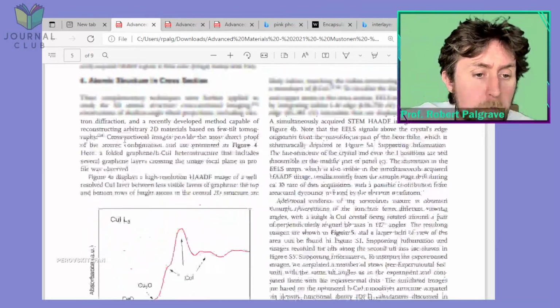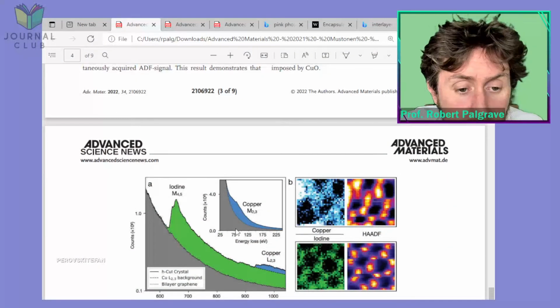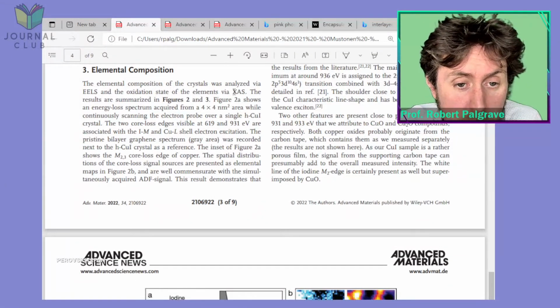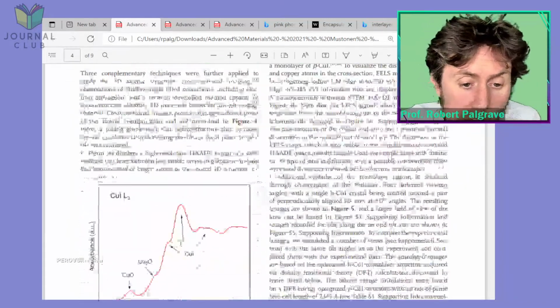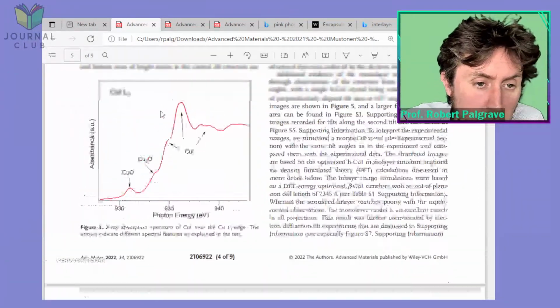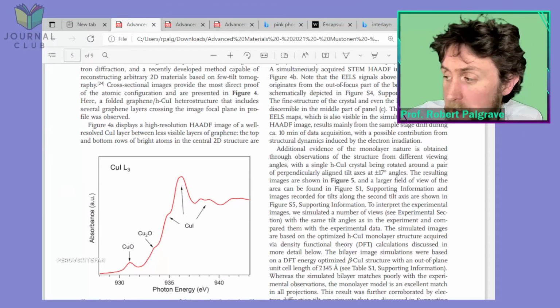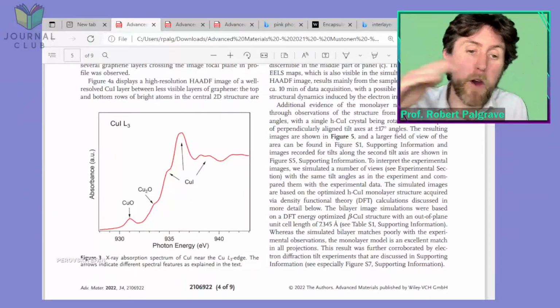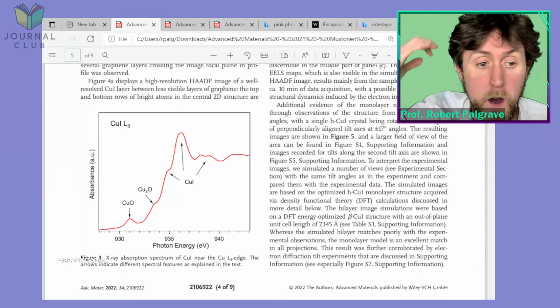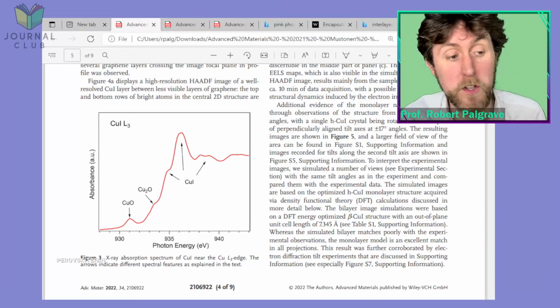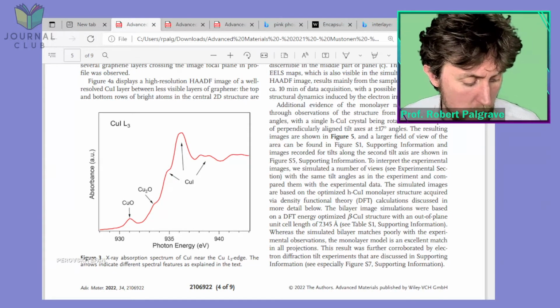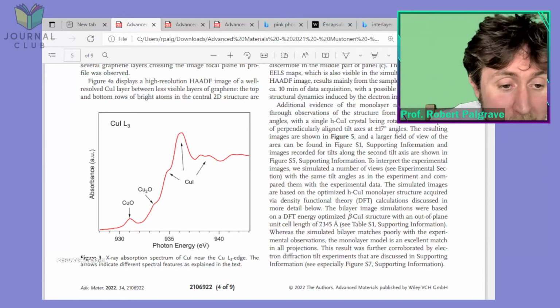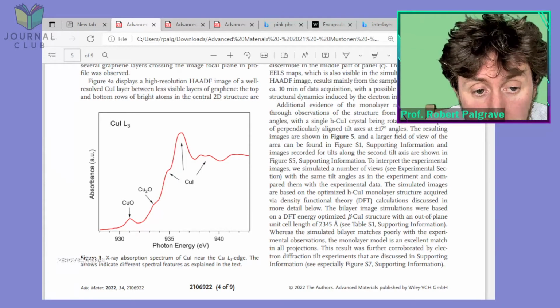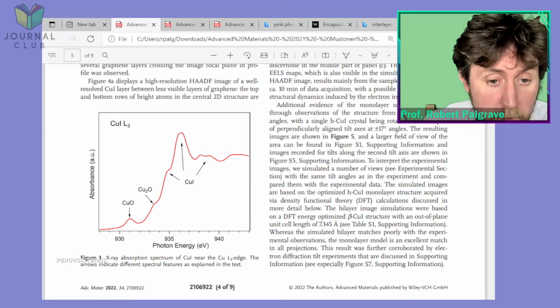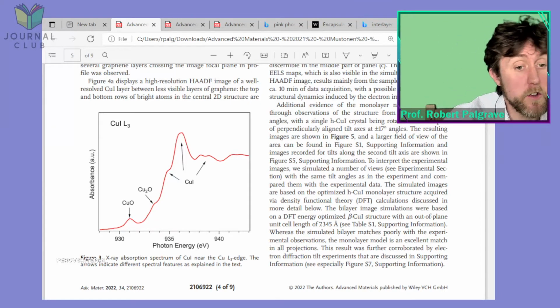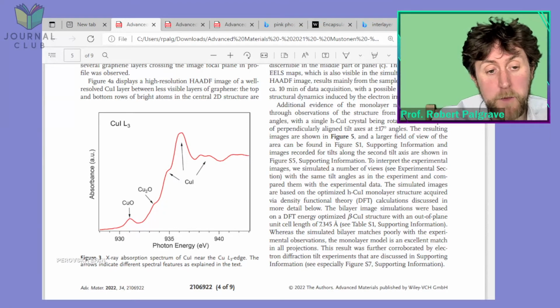Okay, what else have we got going on? So they use EELS to identify that. They use X-ray absorption spectroscopy, XAS, to identify something to do with the oxidation state. So they look at the copper. This is the copper edge in XAS. The copper edge means the point where the copper starts absorbing the X-rays. It absorbs the X-rays because of electronic transitions which go on within the copper. And exactly the shape of this edge, the energy of the edge and the shape of the absorption edge, going from low photon energy here to high photon energy, tells you about a few things actually, but you can get information about the oxidation state.